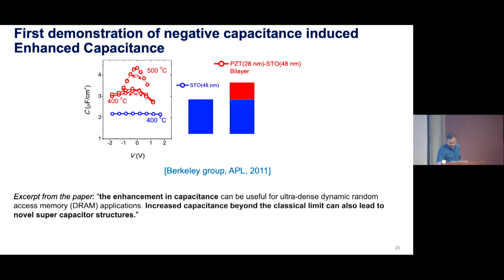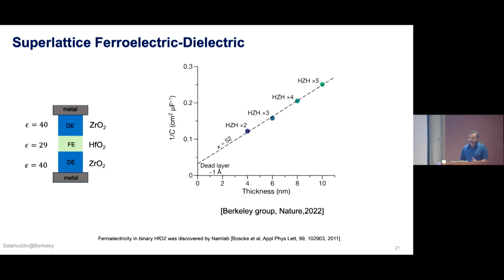Okay, so much more recently what we have done is we have worked on materials that we can actually integrate with silicon transistors, advanced silicon transistors. So here I'm showing a structure where I have hafnium oxide and zirconium oxide in a trilayer fashion. Zirconium oxide has a permittivity of 40, hafnium oxide has a highest permittivity that we can get of around 29, and zirconium oxide, again, another 40. Typically, when we put these materials together, classically, you put capacitors in series, capacitance goes down. But here, what we have been able to show is that you can get a permittivity which is larger than all of these constituent permittivities. So again, this is this non-classical increase in the permittivity of the system. So this allows us to then start using these things for